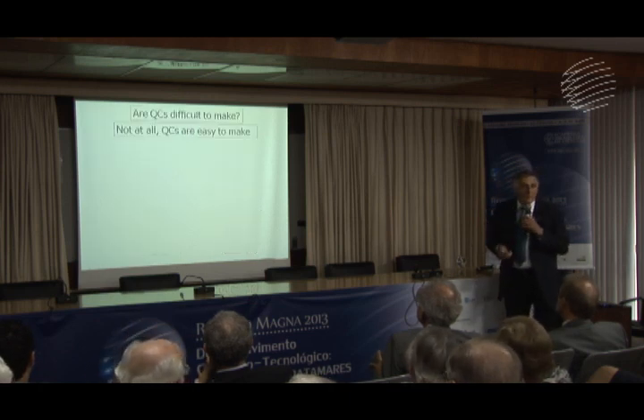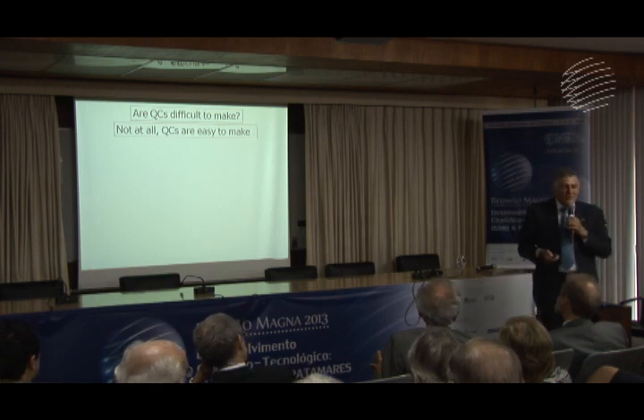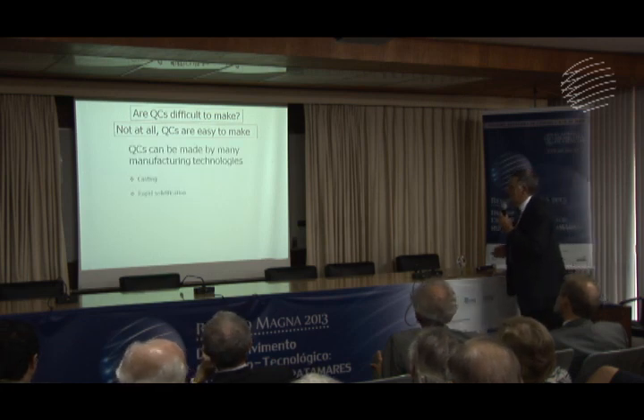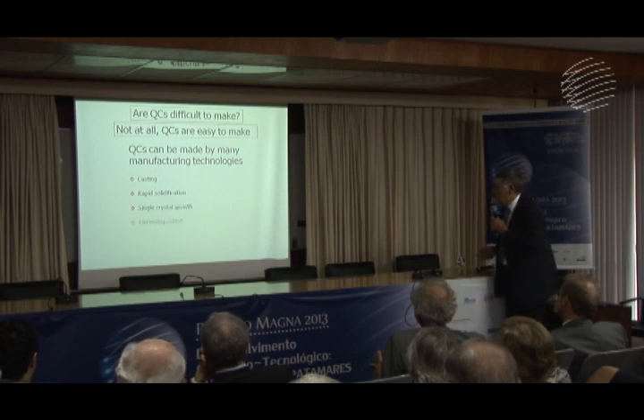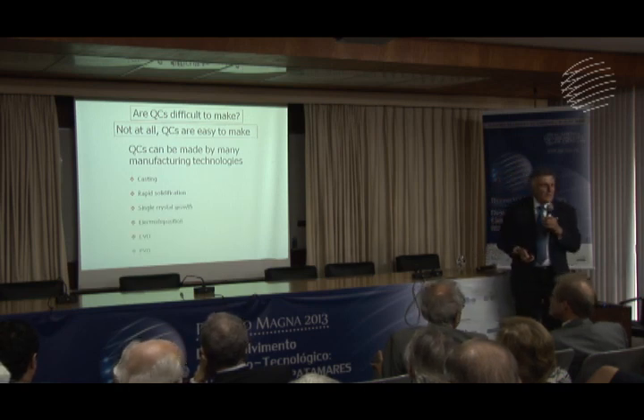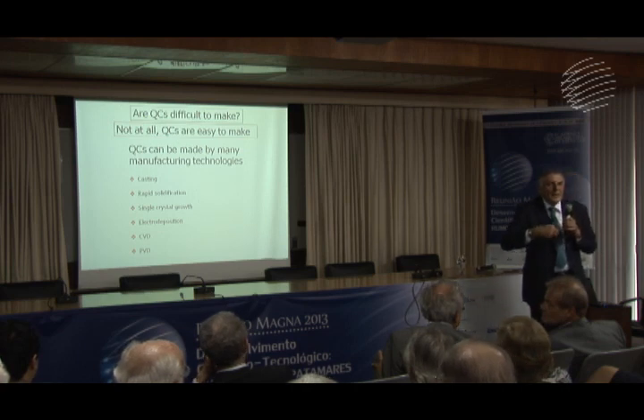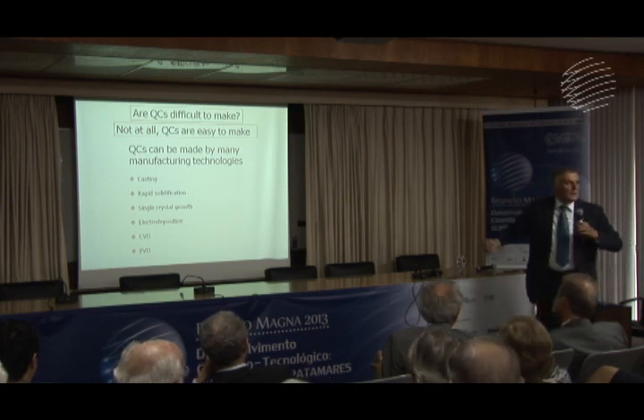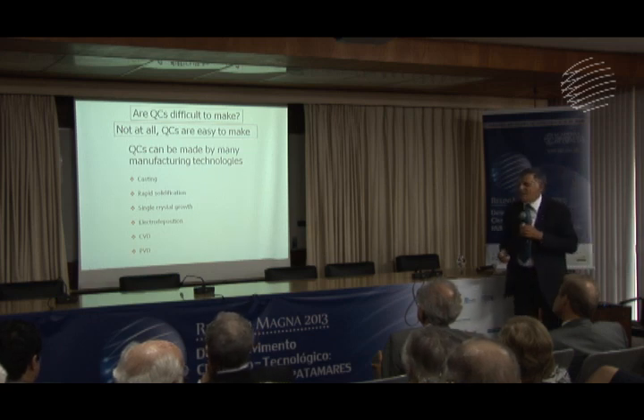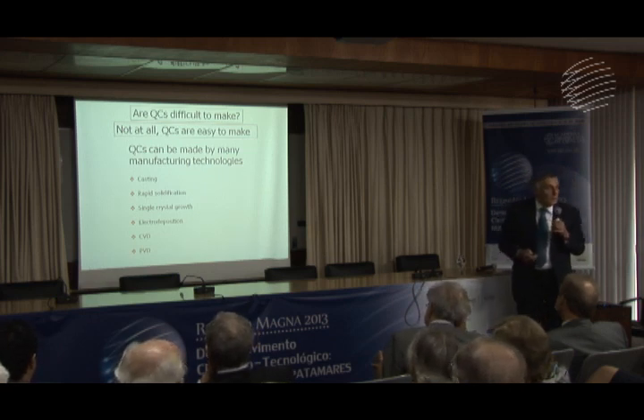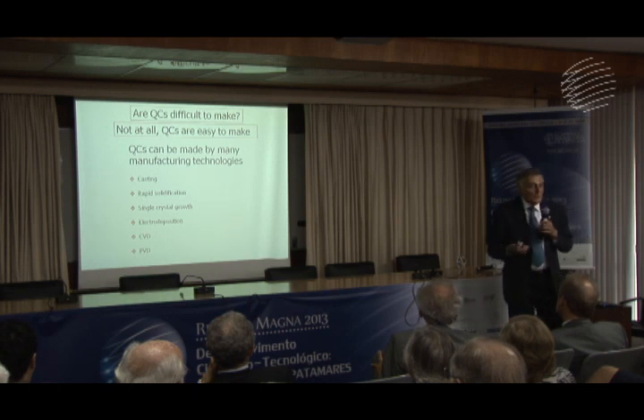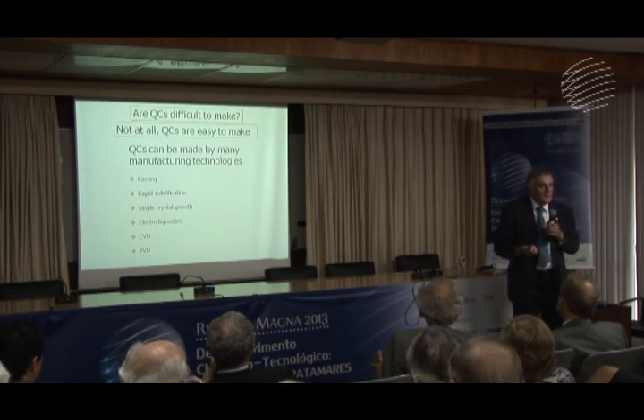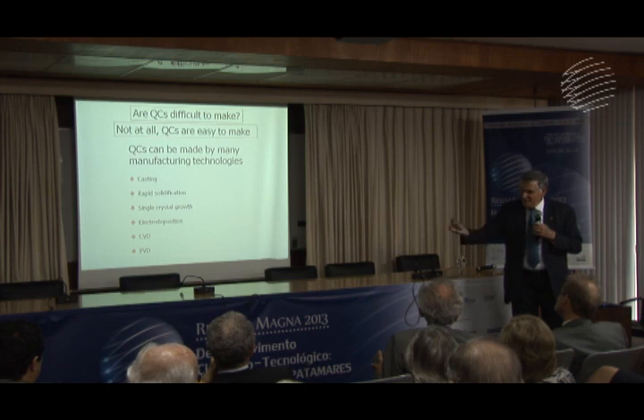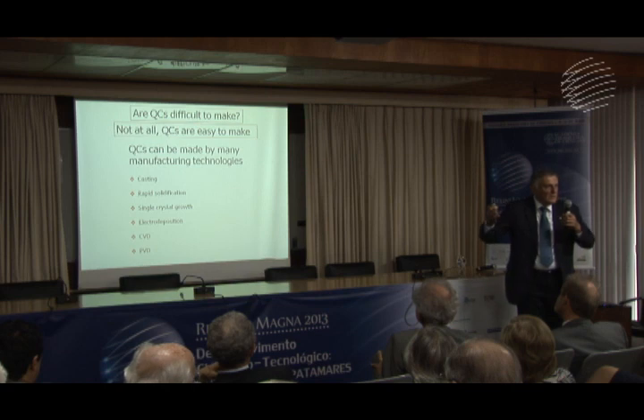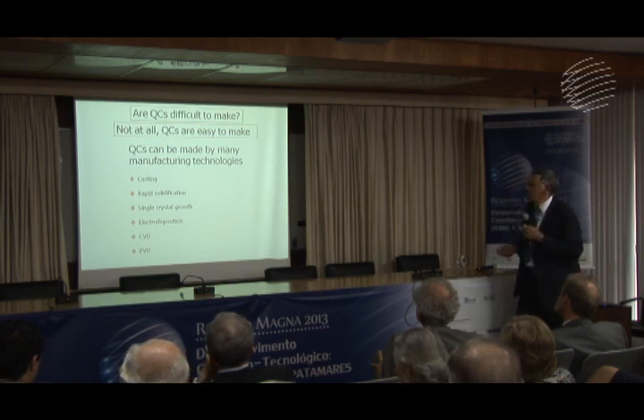Okay, so maybe they're difficult to make. Not at all. They're very, very easy to make. You can make them by casting, by rapid solidification, by single crystal growth, by electrodeposition, CVD, PVD. Any technology that you use to make any other metallic alloy, you can use to make a quasi-periodic crystal. It is easy to do. Are they made of esoteric materials? Not at all. We talk aluminum and iron and copper and titanium and nickel and chromium. You know how many millions of tons of iron are used every year? It's all over the place. No, this is not the reason.